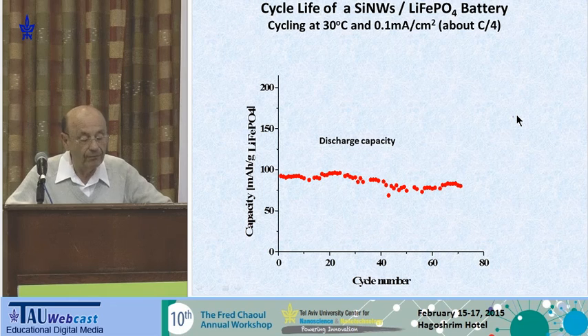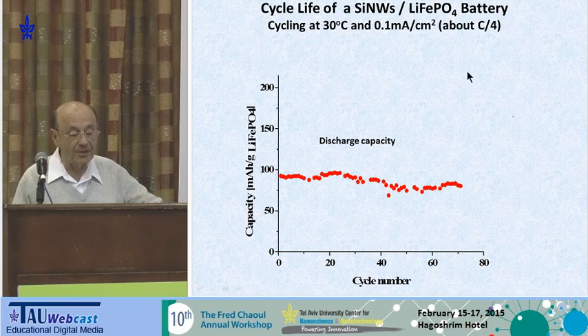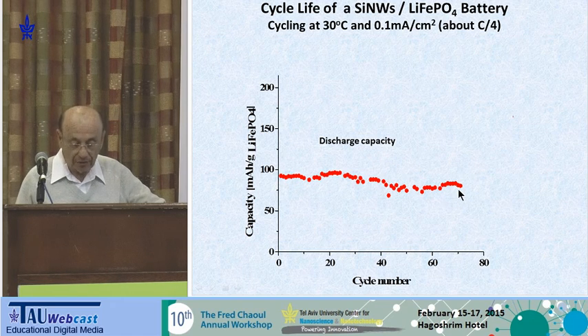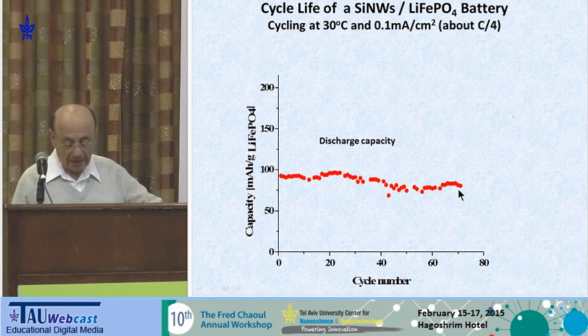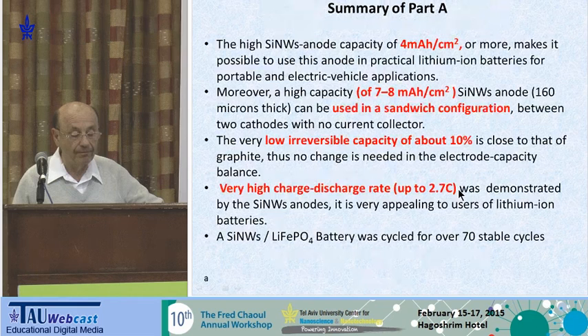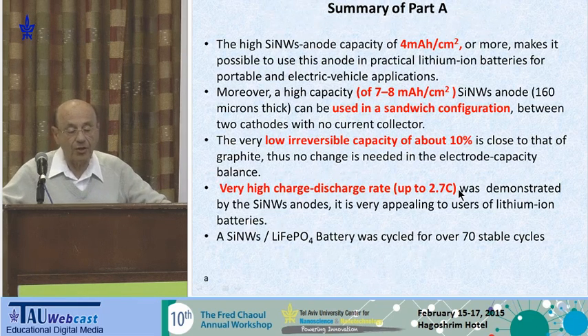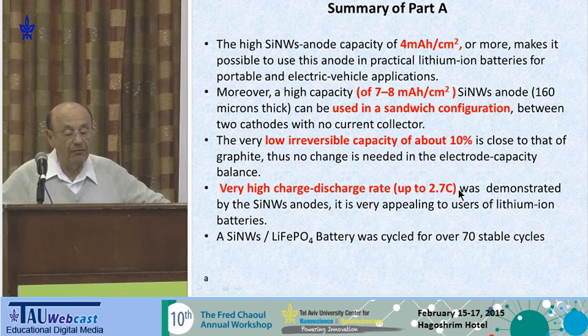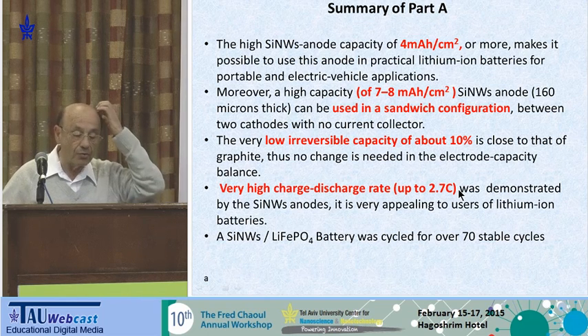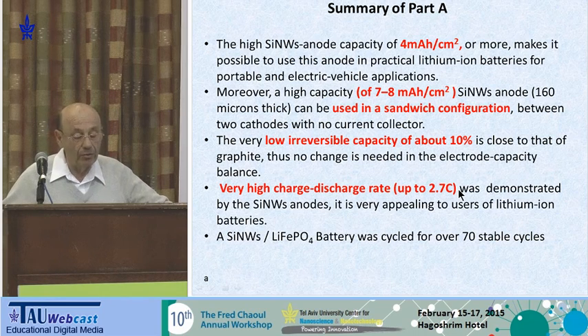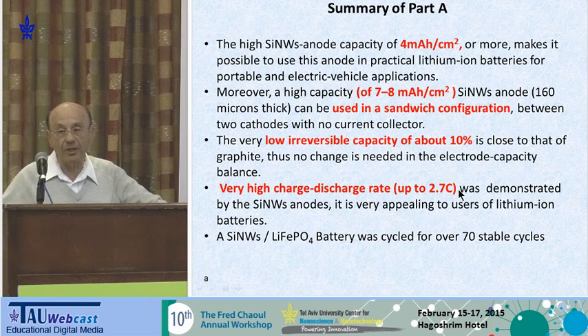This is the capacity of a real battery made of silicon nanowires and a lithium iron phosphate cathode, which is a very popular cathode in lithium-ion batteries, and we got quite stable 70 cycles. That's very important to show that it can work in a real battery and not just in a half cell. So to summarize this section, we are able to build a 4 milliampere per centimeter square electrode, which is important. We even were able to get 8 milliampere per centimeter square. In this case, we can sandwich our anode between two cathodes, and this is very important.